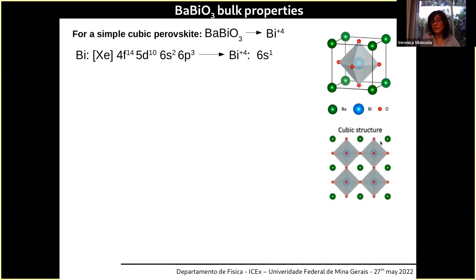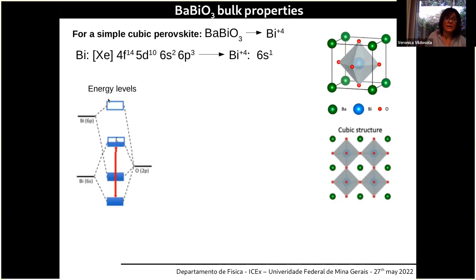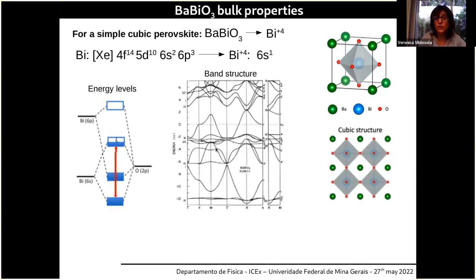And in this projection of the crystal structure, all the octahedra are equal. If you look at the energy level scheme, it is not exactly 4+, because this is an oxide, you have covalent bonds, orbitals that hybridize bismuth with oxygens. You have at the end some hybridized levels, where the last one that is occupied has mostly s character coming from the bismuth, and it is supposed to be half filled if it were like this. In the corresponding band structure, if you do a realistic calculation, you would also have a band with mostly s character, half filled. So you would have a metal, right?